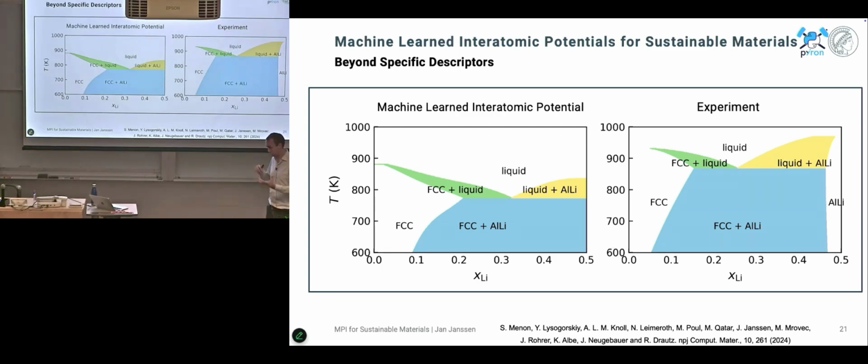But what we also see here, and which raises a couple of questions, is that there might be a dependence on the functionals that we're currently using. Right? So maybe PBE is not good enough to reproduce the experimental phase diagram. And if we're able on this level to compare to experiment and say, okay, maybe one functional is better than another one, that really also helps other people to then say, okay, how can we develop the next generation of functionals? Right? So if we can control the uncertainty on all other levels, like what is the uncertainty in the DFT calculations going into our calculations, what is the uncertainty on the thermodynamic level, where we are currently still extending the models, but we're also able to quantify it there, then we can really do a one-to-one comparison with the experiment. Good, so we can really get the phase diagram.